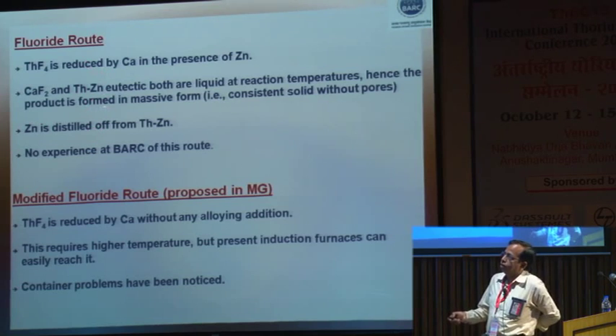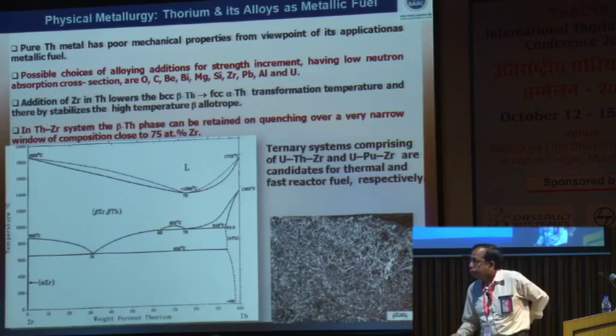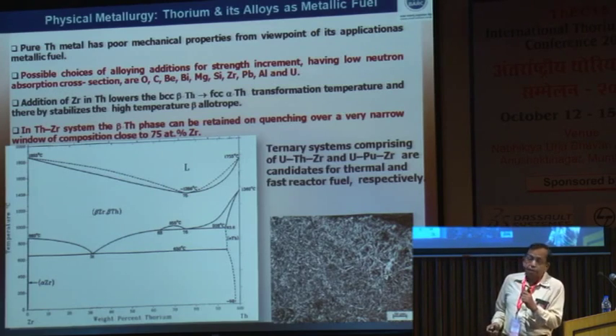Instead, what we have done is we have used thorium fluoride and calcium, and we have not used zinc. And here the temperatures will be higher, so that is the disadvantage. So there is a container problem, but we are about to overcome this, and this will be a good technique for making good quality thorium from the starting intermediates. Now, that was about extractive metallurgy of thorium.